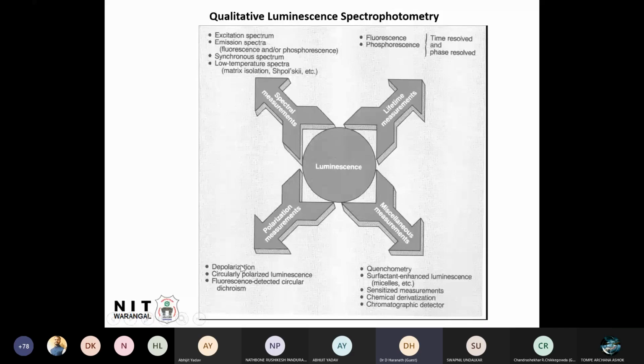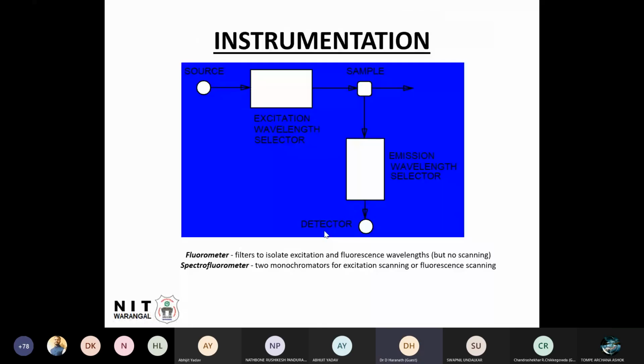So a simple arrangement is like this: you have a xenon source, and there is an excitation monochromator, or you can call it a wavelength selector, because all wavelengths are being given here. It will select one particular wavelength to fall on the sample, which is kept at an angle of 45 degrees. Here the sample holder is drawn at 90 degrees, but it will be kept at a 45 degree angle. Light will fall and reflect, and there is an emission monochromator where it will record that spectrum, and there is a detector and a PC where you can see the spectrum.